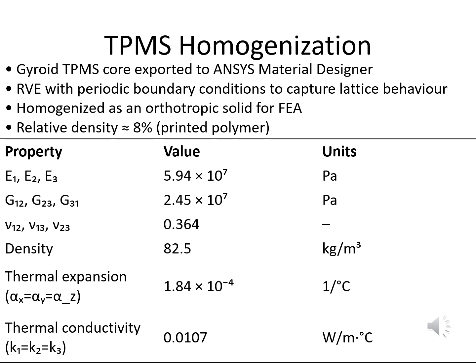For a chosen relative density of approximately 8%, the homogenization produces an effective Young's modulus around 59 MPa, shear modulus near 25 MPa, and a density of 82 kg per cubic meter. These values match well with published experimental data for polymer TPMS structures. Once homogenized, the material model replaces the complex lattice geometry and can be used directly in static, dynamic, and thermal analysis. This greatly simplifies the model while preserving the key physics of the TPMS behavior.